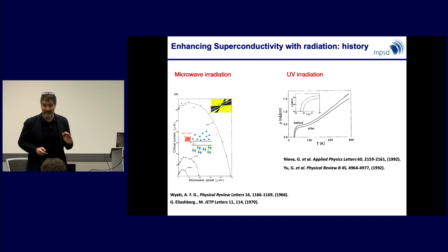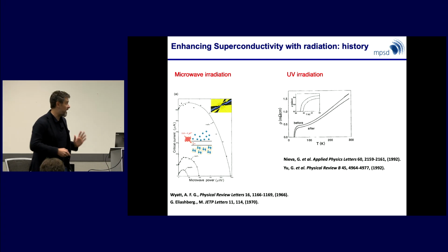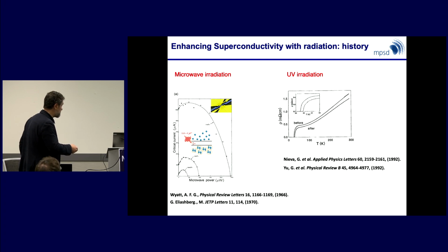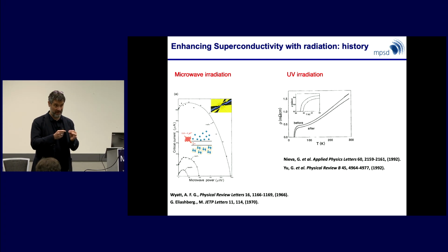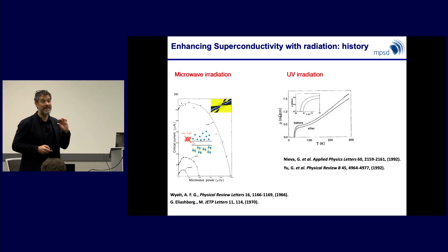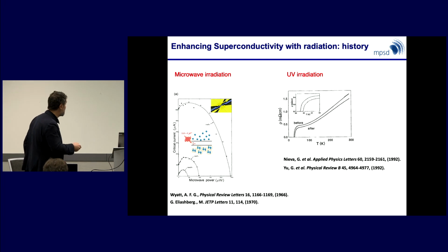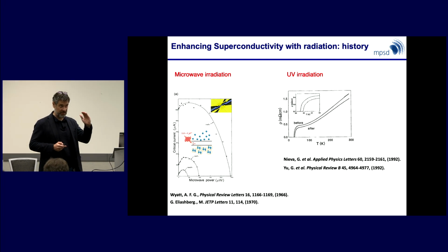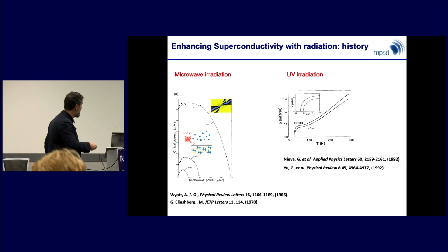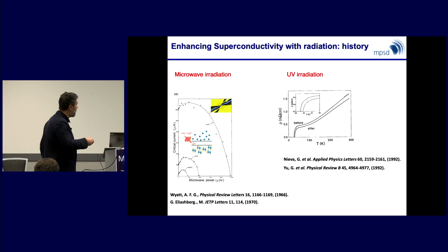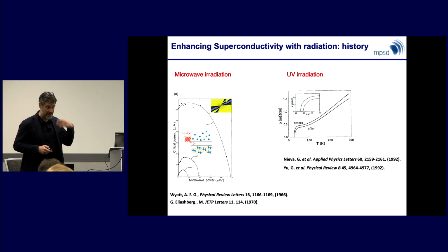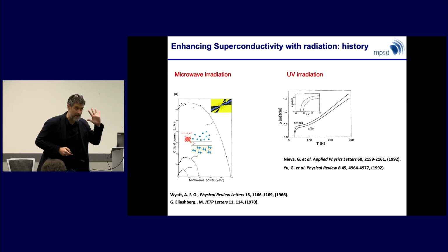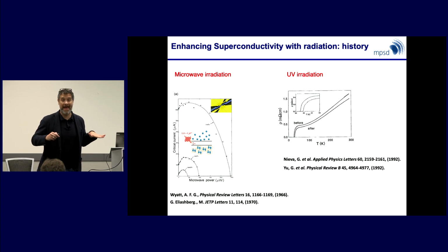This business of photo-enhanced superconductivity has a long history. In the 1960s, there were very interesting experiments in which certain microbridges of BCS superconductors were irradiated with microwave radiation at frequencies below the superconducting gap. What they observed were enhancements in the transition temperature by some fraction of the transition temperature and enhancement in the critical current. There's a very beautiful theory by Eliashberg that posited that excitation below the BCS gap would redistribute the Bogoliubov quasi-particles above 2 delta, thereby fooling the self-consistent BCS equations to think that the material would be at lower temperatures than it actually would be. And this would explain the observations.